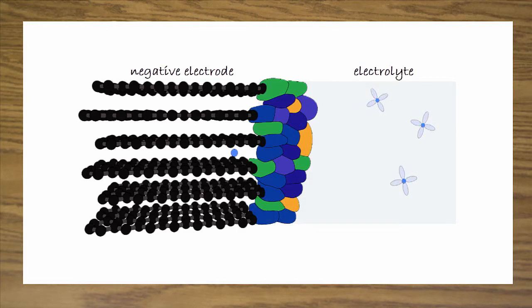This layer of product on lithium metal or graphite is called the solid electrolyte interface, or SEI. It is believed to have a mosaic structure composed of different degradation products, such as lithium oxide, lithium fluoride, lithium carbonate, or oligomers. Its formation is detrimental to the battery because it is irreversibly consuming lithium and electrons. However, the formation of this SEI layer is also kind of a miracle that allows our battery to work.